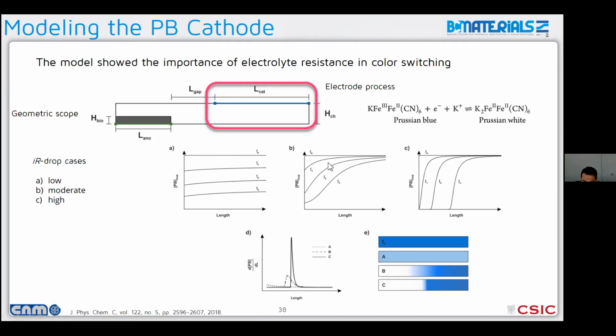So one way to look at this was to do the derivative of this surface concentration with length, and we got these peak plots, and the peaks are actually an indication of the current density going through the system. So it can also give us an idea, when you look at the width, of the magnitude of the IR drop. So for example, when there's little IR drop, there is no peak because the change is happening more or less homogeneously everywhere. As you increase the solution resistance, you start getting this peak. It's quite broad, as is the area where you have a color gradient. And then when you make the system more resistive, you get a very sharp color change.